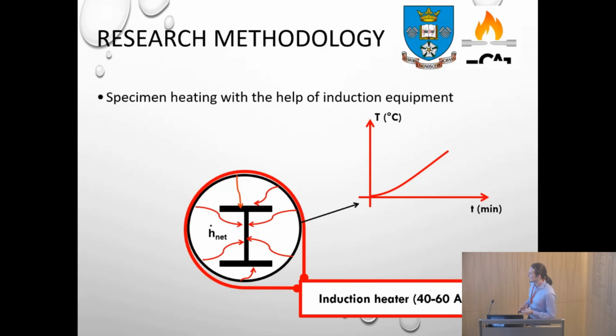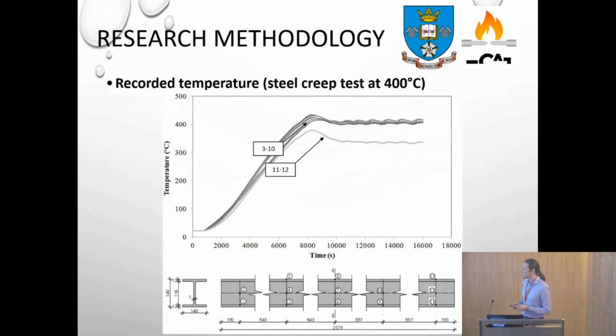With this kind of heating arrangement, we can get more uniform temperature inside the tube itself and onto the specimens also. This is just a recorded temperature that we can get when we test steel columns inside. These are the points in the middle of the column. You can see them placed here. At the end side of the columns, we can get a bit lower temperature because the electrical field is a bit weaker at the end of the tube. But overall, if you compare the top lower flange and the web, you can get a pretty uniform temperature within the length of the tube.